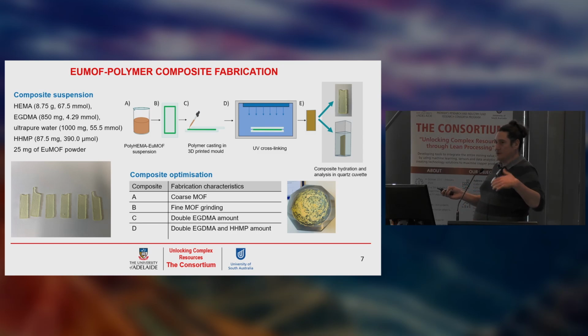We take the monomer MOF solution or suspension. We then put that into a 3D printed mold. There's a photo curing agent there, so it cures the monomers, and we form this composite. So you end up with these relatively transparent composites with the MOF embedded within the polymer matrix. So these can then be used initially to assess how the composite responds to different ferric iron concentrations.